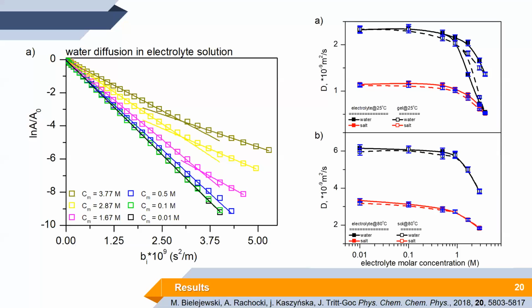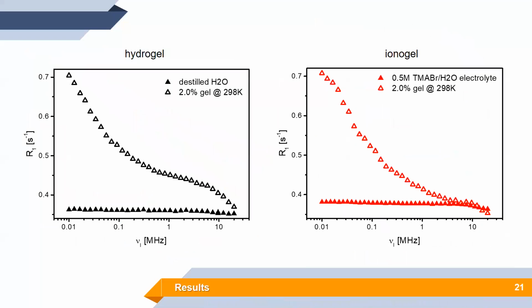However, because of the specific experiment, and also because the amount of the gelator is very small, on the level of 2 weight percent, with this pulse-field gradient method we are not actually able to see what happens at the surface of the gel matrix. So to be sensitive to these interactions and to the part of the system which takes place at the surface of the gel matrix, we turn to field cycling NMR.